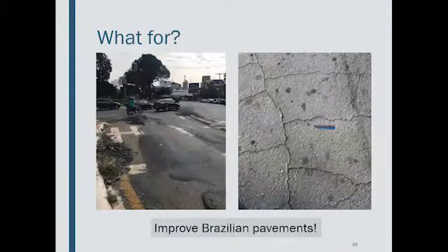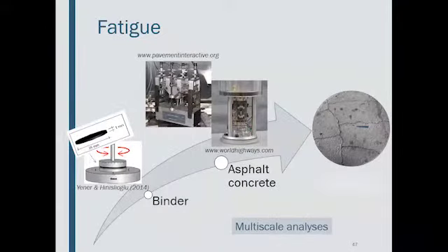And why do I want to study hot mix asphalt? It's because, unfortunately, in my city, I see this every day. We see several problems with rutting and cracking, so I think it's important to improve our pavements. And in terms of fatigue, we can work in the lab using many scales, trying to predict what will happen in the field. It's common to work at the binder scale by performing tests in the rheometer or doing many tests at more real scales with the asphalt concrete samples.